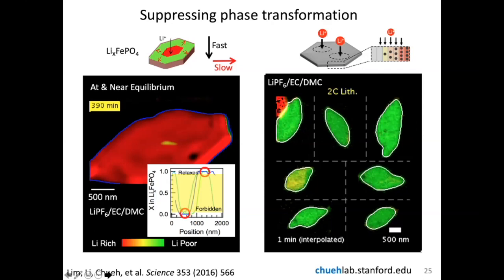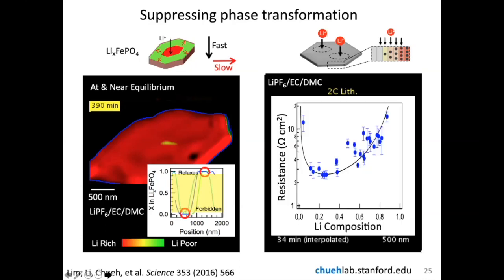So rather than forming this nucleus and growing, you actually see continuous lithium composition that goes through the miscibility gap. So this is thermodynamically forbidden. So you no longer see the phase boundary, and instead you see a continuous filling and unfilling. So why are we violating thermodynamics here? Well, it turns out this has everything to do with the non-equilibrium thermodynamics of the system.